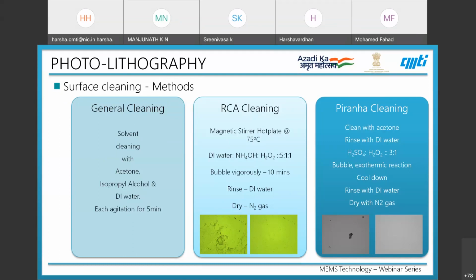The RCA cleaning has a particular setup with a magnetic stirrer and a hot plate, set at 75 degrees centigrade. We mix DI water, NH4OH, and H2O2 in the ratio 5:1:1 and bubble it vigorously for about 10 minutes. If it is RCA1, we use NH4OH, and if it is RCA2, we use HCl. The classification is based on what type of contamination we expect on the wafer.